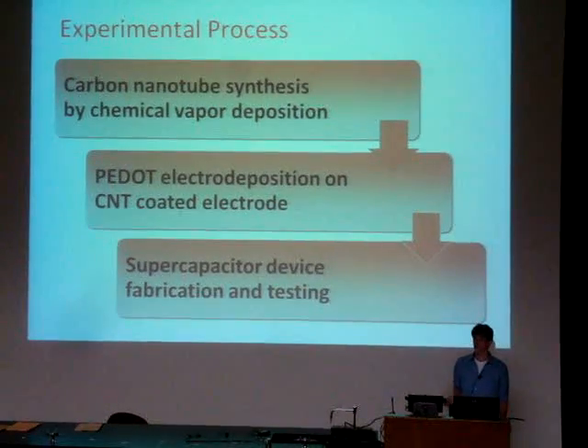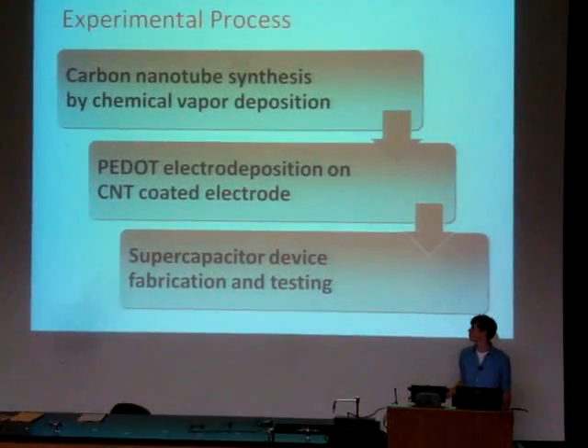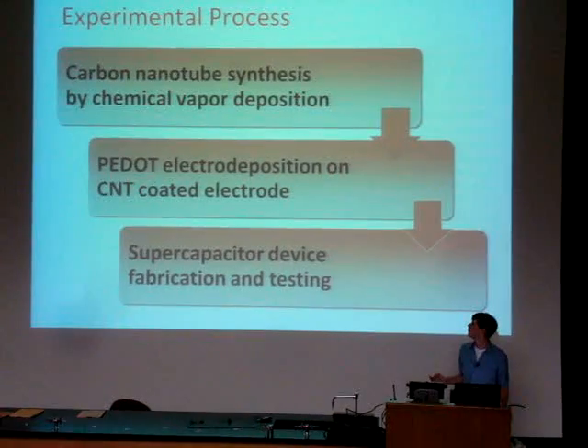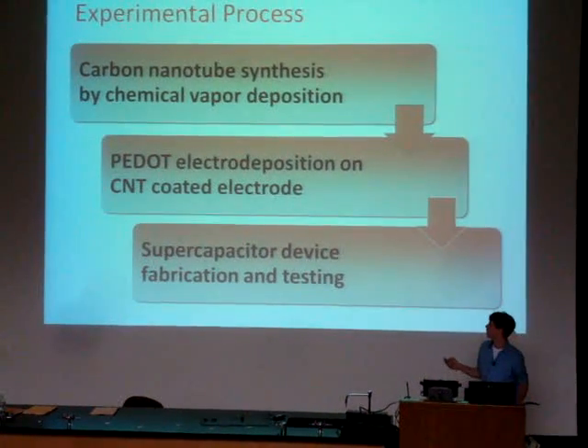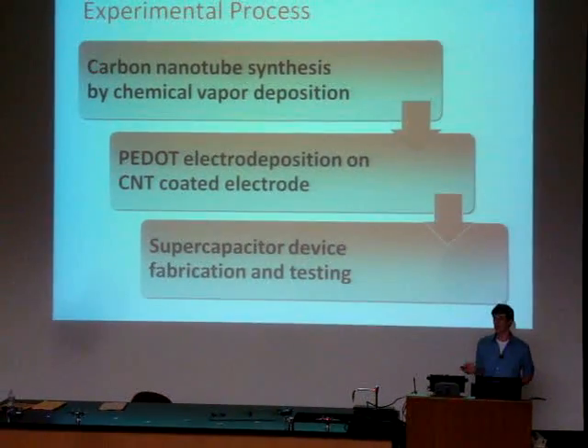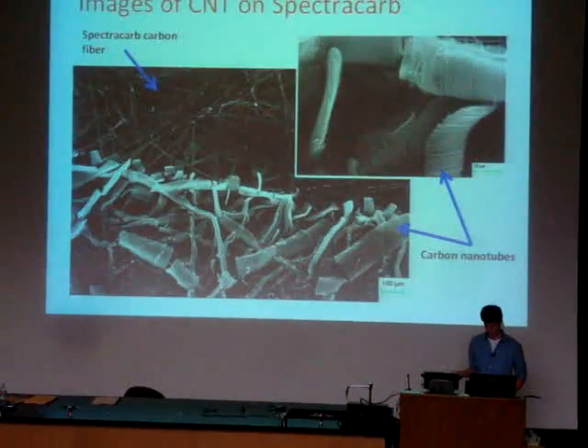So this slide simply depicts the experimental process. We started with carbon nanotube synthesis via chemical vapor deposition. Then the PEDOT was deposited on the carbon nanotube coated electrode. Then we made the supercapacitor and tested it.